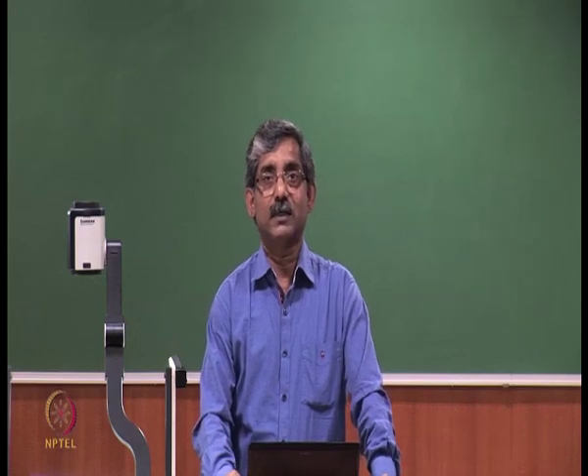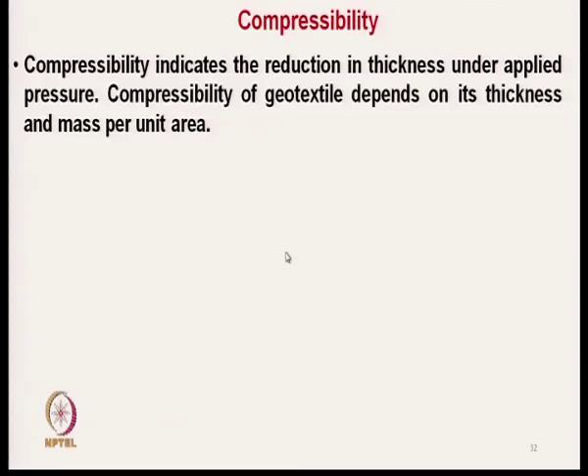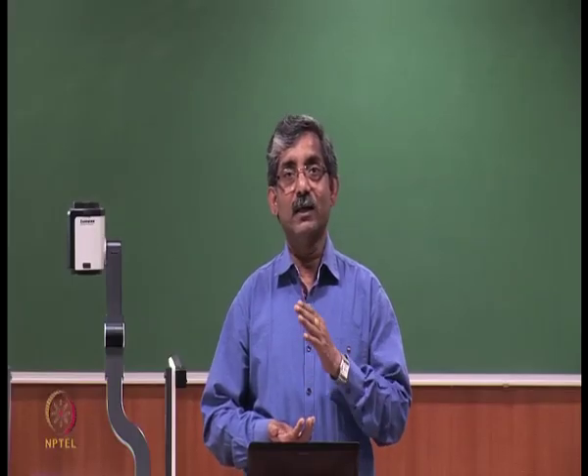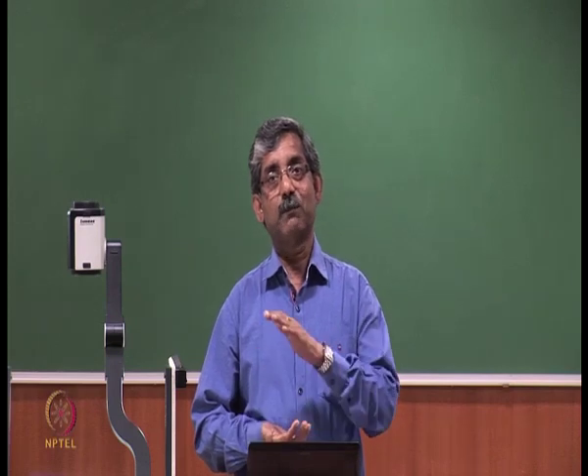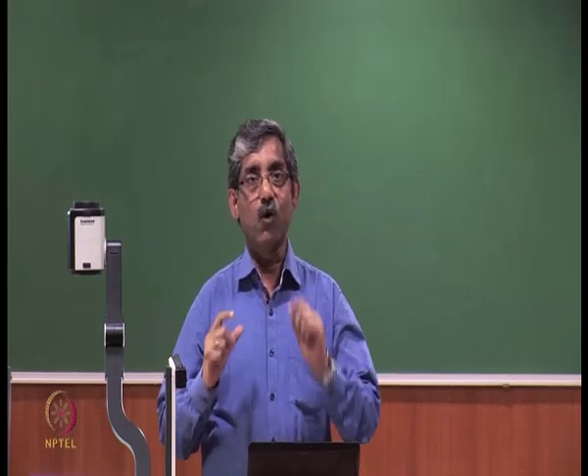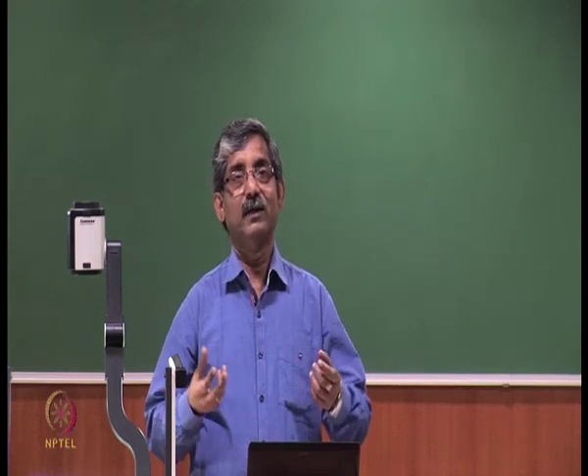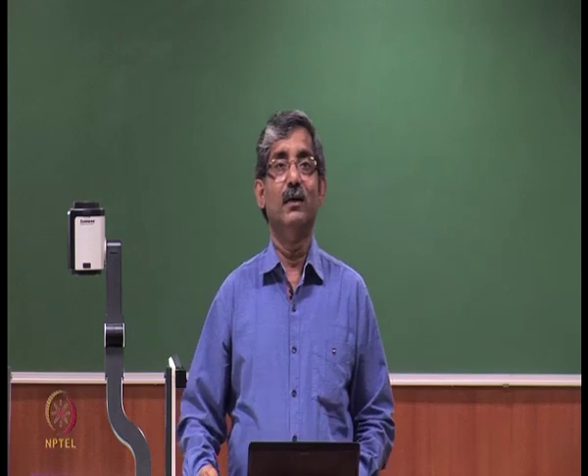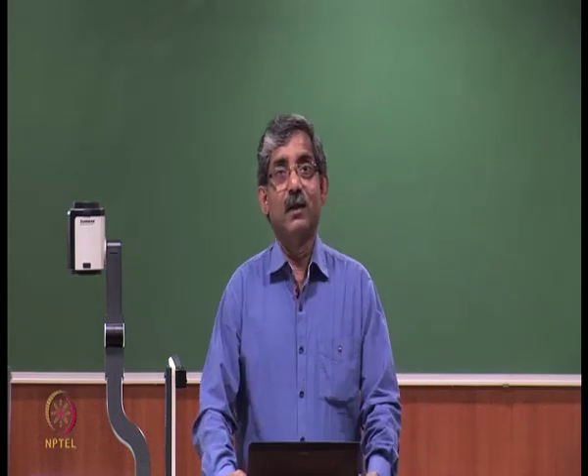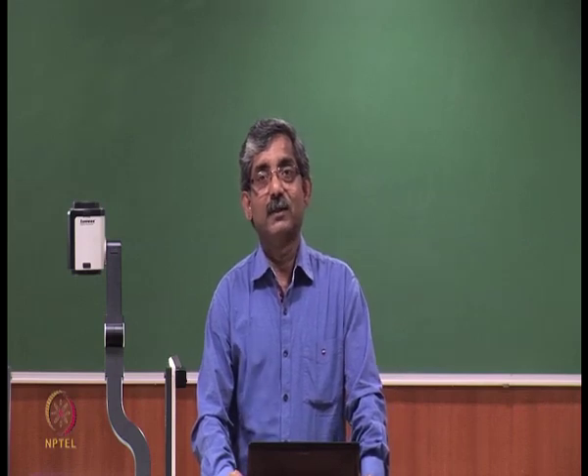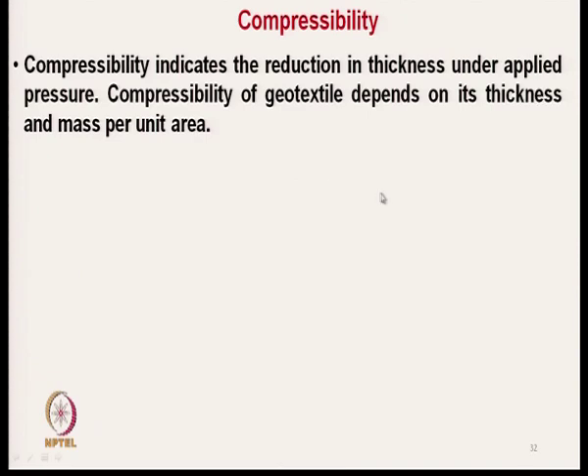Now we will discuss compressibility testing. Compressibility indicates the reduction in thickness under applied pressure. It is very important for geotextile as far as water transmission — transmissivity or permeability — is concerned. If the geotextile is highly compressible, once we apply load the pores of the geotextile will get compressed, and its transmission characteristics will be affected.